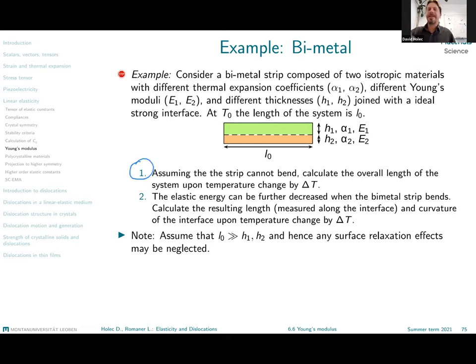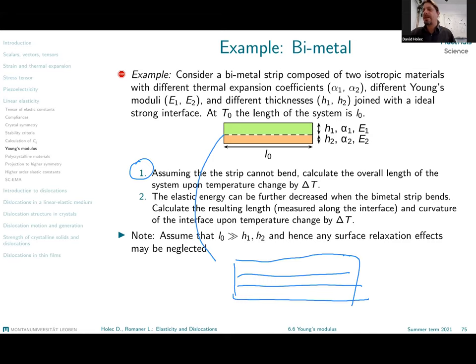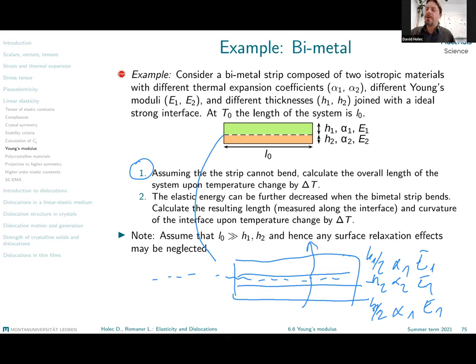This first task, where you should assume that the strip does not bend, is probably a little bit academic, but you can imagine it as a trimetal, where you would have three layers, made symmetrical: H1 half, alpha 1, E1, then H2, alpha 2, E2, and in the bottom layer, the second half of the first layer. Such a situation is symmetrical with respect to the horizontal axis, and therefore such a sample would bend neither upwards nor downwards, and you would end up in exactly the situation that we assume here, that the bimetal strip does not bend. So it is not only a hypothetical example which doesn't make sense. No, it actually corresponds to such a situation.